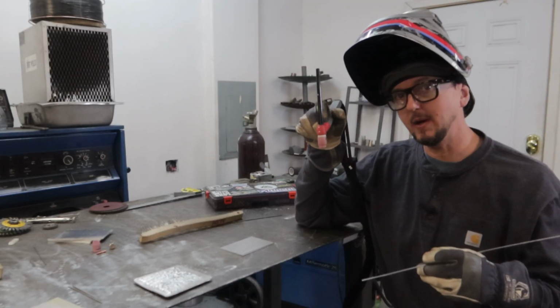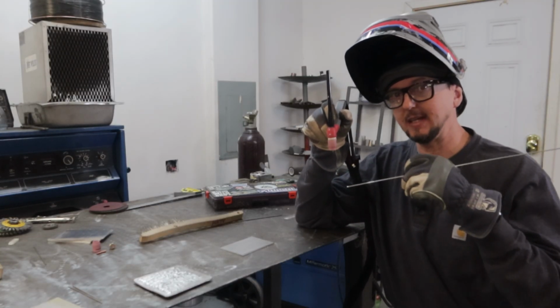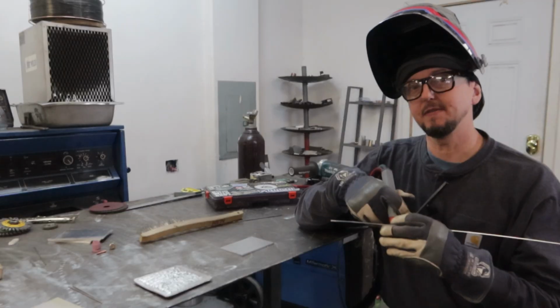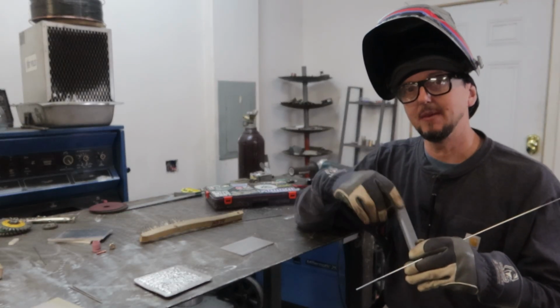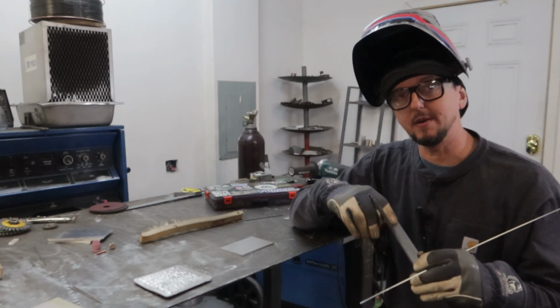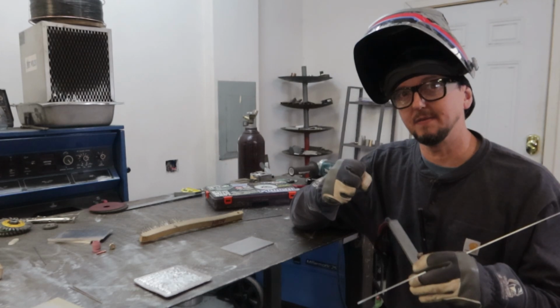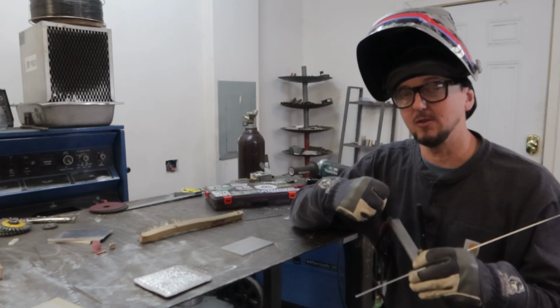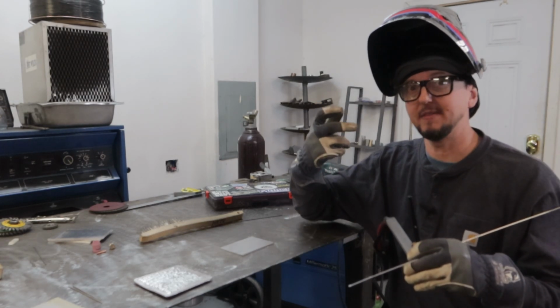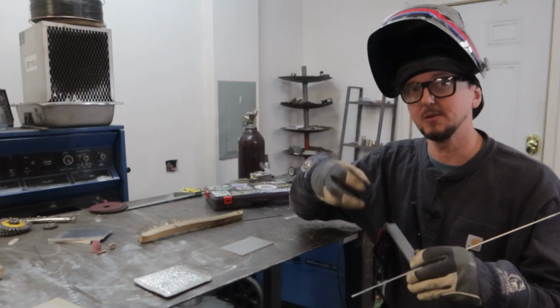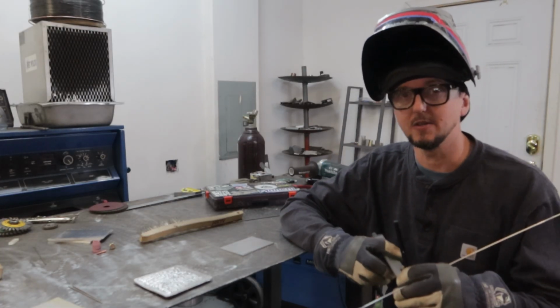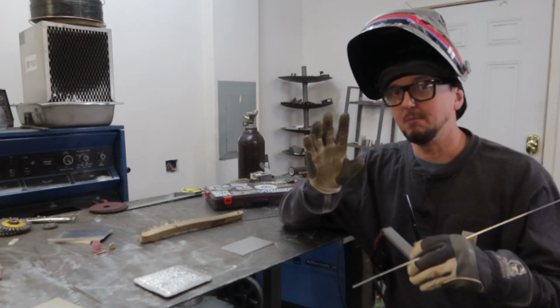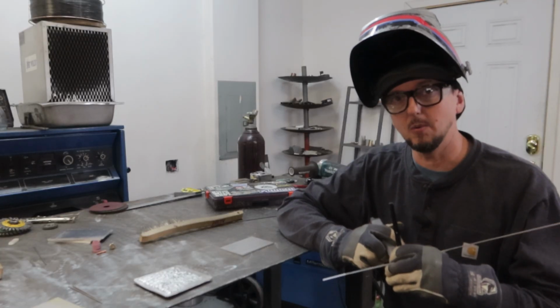So, if you don't wait for that and you go to put this filler metal in, it's just going to ball up on the surface, and then that AC circuit that's going back and forth, a lot of times it will suck some of that loose filler metal on the surface against your tungsten, and it'll just kind of blow up and you won't really know what's going on.